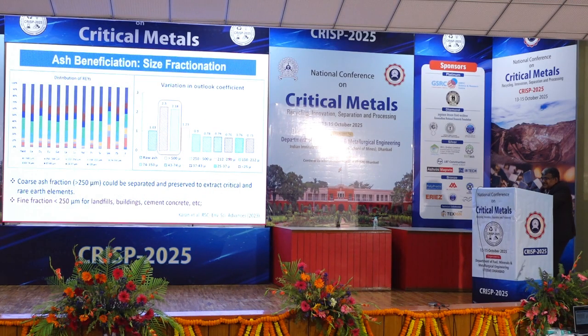Coming to beneficiation, the distribution in particle size is also good. In the coarse particles, the enrichment coefficient is very high. So what we suggest is, can we separate the coarse particles and go for rare earth extraction, and the rest can go for landfill.